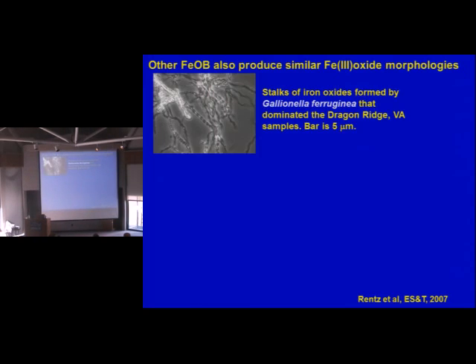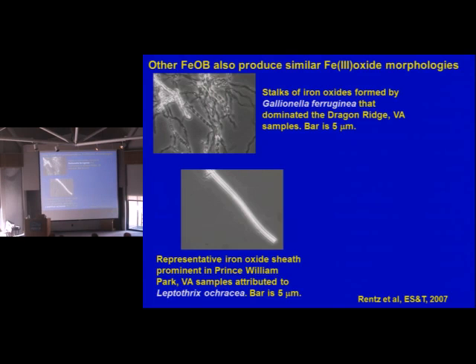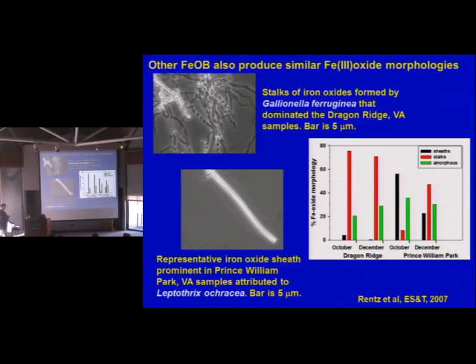So we did some other experiments with other organisms, and this was with Dave Emerson at places over in Virginia before he went back to Maine. This is Gallionella. This forms nice stalks. And then here's a Leptothrix, which is forming the sheath. And what we did was we did an experiment at these 2 sites in October and December.